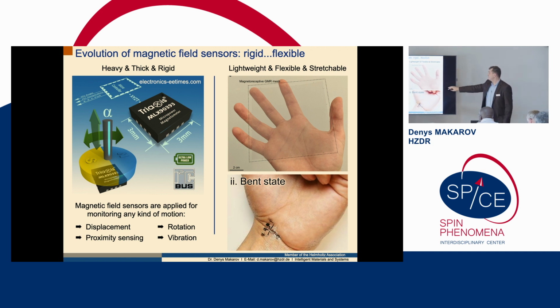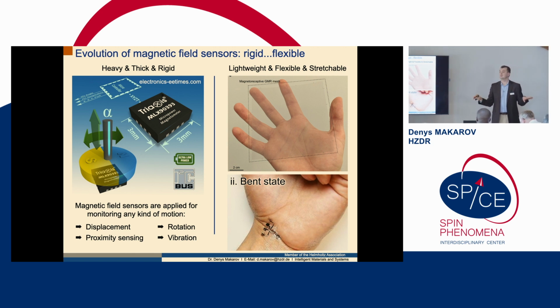And this is what you can do now in batch processing in conventional sputter chambers, right? There is no problem to take a 300 millimeter wafer. You can put a stack of them. You can laminate them with polymeric foil of your choice. Can be Kapton, can be polyethylene, whatever you want in principle. And on these foils, you can do deposition of thin films. You can do lithography, you can do GMR, you can do AMR, you can do basically anything you want.